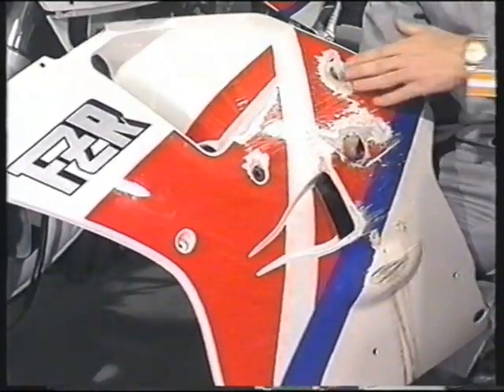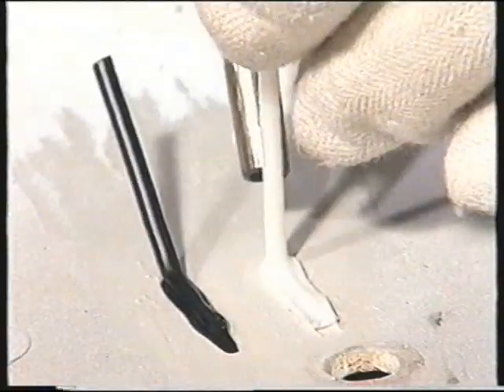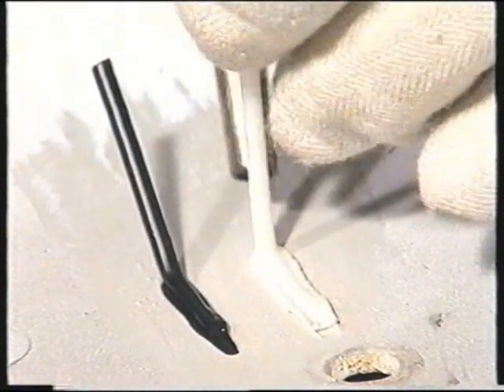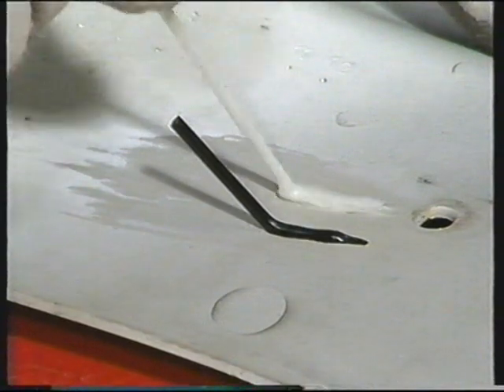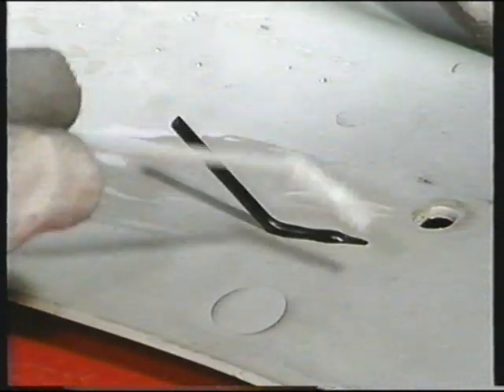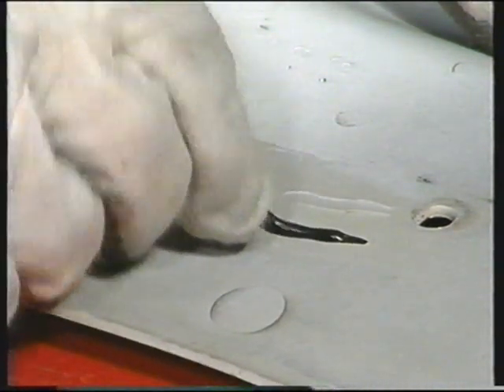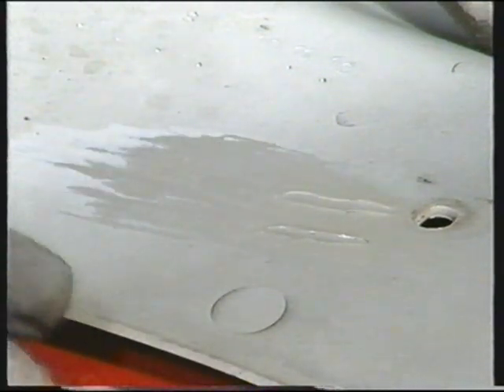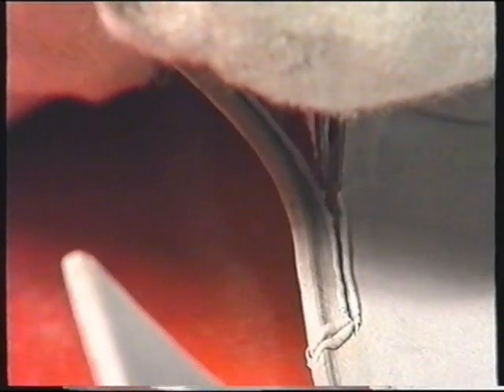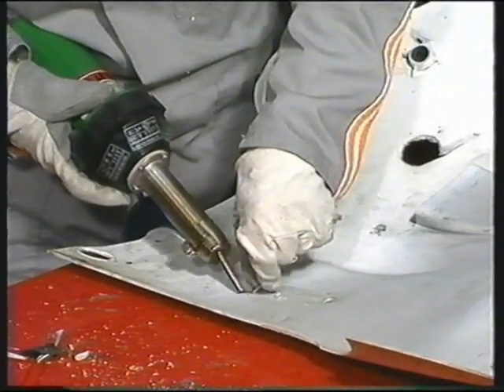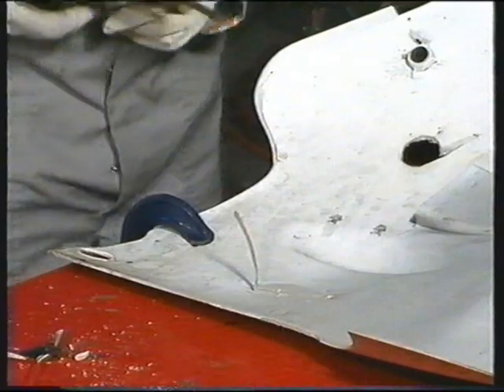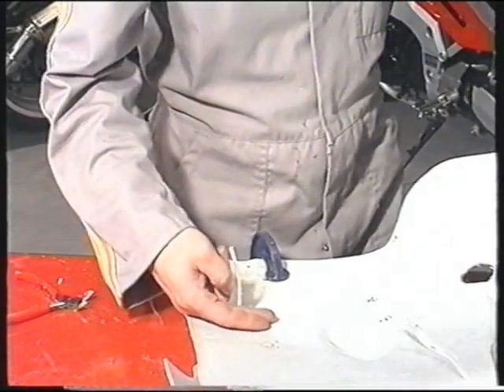This side fairing of a Yamaha bike, although apparently thermoplastic, appeared to be neither ABS nor polypropylene. In cases like this, where identification is difficult, it's usually possible to cut self-made welding rod off a scrap panel, thus guaranteeing a match. However, this material proved impossible to weld, even by this method, but as we'll show later, it is still repairable.